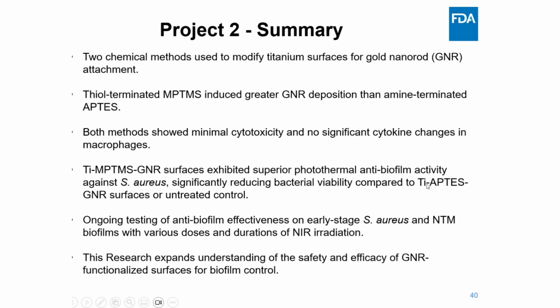So to summarize this project, we used two chemical methods, amine-terminated silane, APTES, and thiol-terminated silane, MPTMS, to functionalize titanium surfaces with gold nanorods. MPTMS led to greater gold nanorod deposition than the APTES. Both coatings were biocompatible, but only the titanium surfaces coated with gold using MPTMS showed effective photothermal biofilm reduction after NIR exposure. So ongoing work is focused on optimizing this approach more for broader biofilm application.